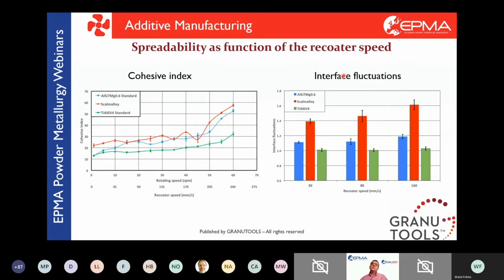And what we noticed is that it was scalmalloy, then aluminum alloy, then titanium. And here we have the same sorting - scalmalloy is on top, followed by aluminum alloy, followed by titanium. And here we can see we are stopping the experiment at 160 millimeters per second.